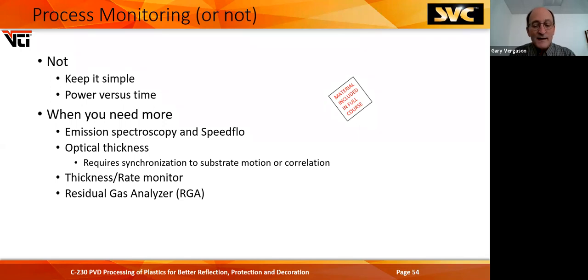One thing that we're always involved in is trying to make that operating window as big as possible, so that when everything is clean and really nice, you can start up here, and then as the process degrades, which it will, with dirty fixtures, dirty chamber, cathode erosion, you get down to where you need to do something. Maybe you've spent a few shifts or a few days getting there, and then you clean it back up and you're back to normal again. So in the case of liners, you need to have multiple sets of liners. So you pull out a set, you put a clean set in as quickly as possible, and you're back in operation.